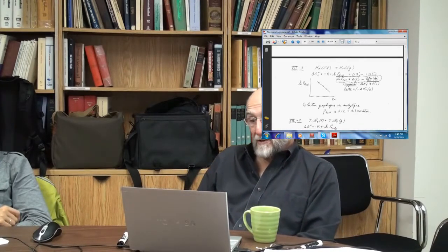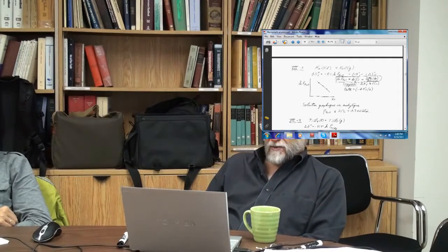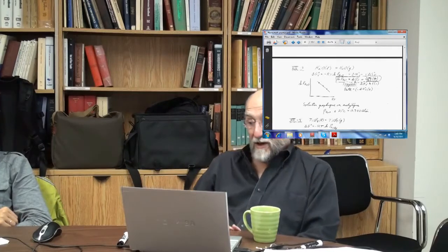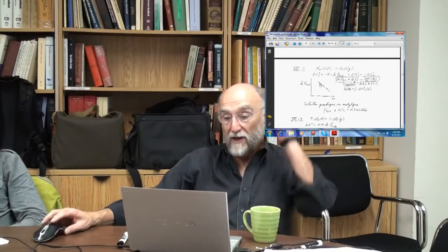The difference, of course, is the integral of delta Cp over T, which is not 0 by any means. This is not maybe the greatest approximation, but if you only had 2 points, then this is the only way you would do it. And since you're only going 25 degrees, it's probably not too bad. So assuming the heat of vaporization is not a function of T, if I just take the 2 points here, I can extrapolate them up to 75. I could just draw a straight line between these 2 points and extrapolate it to 75 degrees. Well, I did a graphical solution. Or you could get the heat.